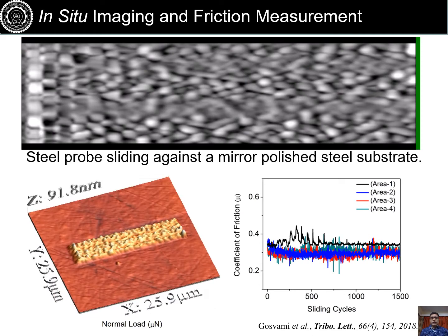So we found that the film growth appeared to be very similar to what we have seen in single asperity contact. Of course, if we press harder, we see that film growth is faster, and it also happens faster at elevated temperature. So we could manage to do experiments in very controlled condition with very controlled geometry, which allows us to understand in a better way how these molecules are reacting at the sliding interface. And in a multi-phase system, it can become very important because you want to see how these local reactions are happening if you have heterogeneity on the surface and so on, which I will demonstrate as well.